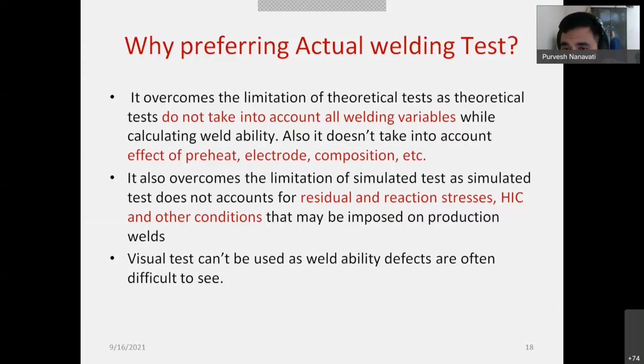But if they are not relieved, they will also aid poor weldability. They will also aid the crack phenomena, and result in poor weldability. Then there is hydrogen-induced cracking, of course, because hydrogen has a tendency to lodge in the most disturbed microstructure, and martensite or a high residual stress microstructure is a very potential site for hydrogen.